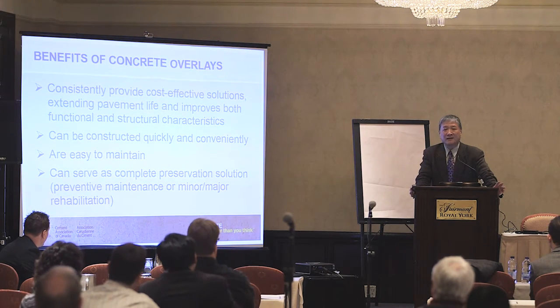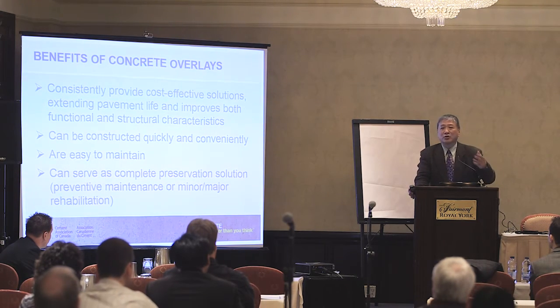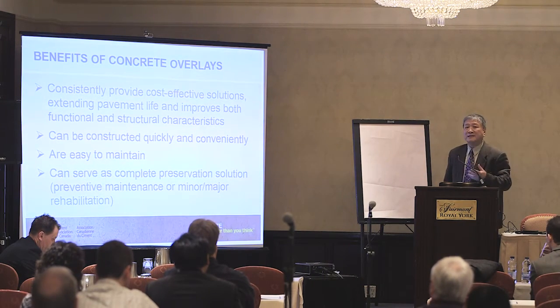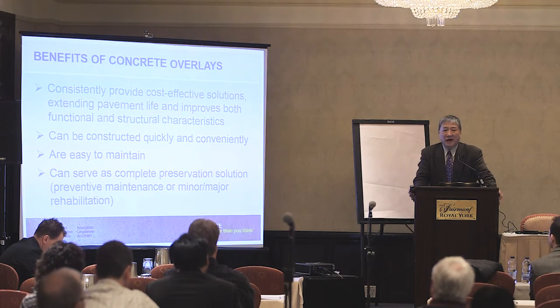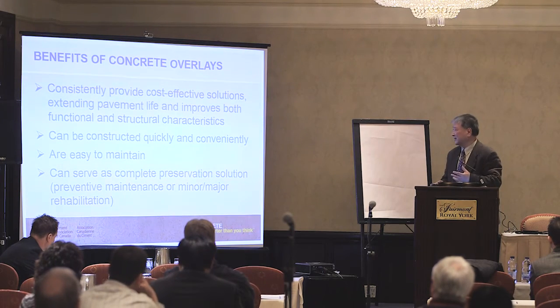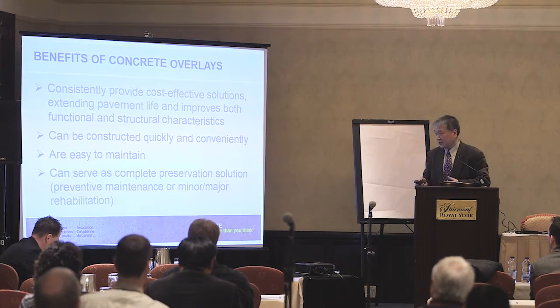and yes, it does take 28 days to reach compressive strength, but the opening strength of 20 MPa for traffic can be achieved in as little as six to eight hours — as the case studies will show later with actual testing results. Concrete overlays are very easy to maintain and generally do not require major maintenance, as you'll see from the Bluewater and Oakland and Sprex Road construction examples. It can serve as a complete preservation solution including preventive maintenance, minor, and major rehabilitation.